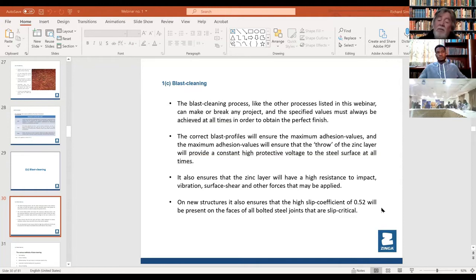Okay. If you use hot dip galvanizing, your slip coefficient is only 0.31. So that means under movement, those bolts can move on the shiny zinc galvanizing. So with Zinga at 0.52 slip coefficient, your bolts are going to remain locked forever. They'll never ever move. So that structure is structurally sound compared to a hot dip galvanized structure. It's a big point that. And again, if you guys have any questions on this at any time, please.